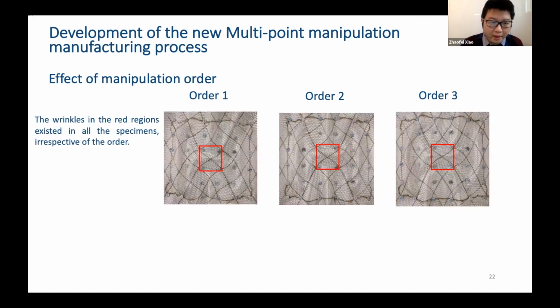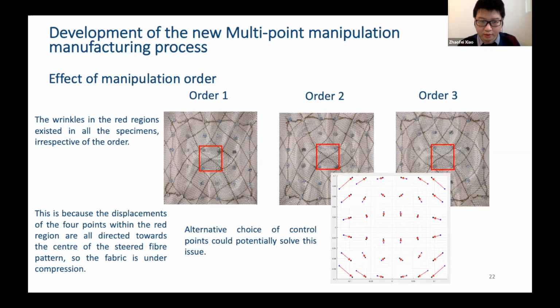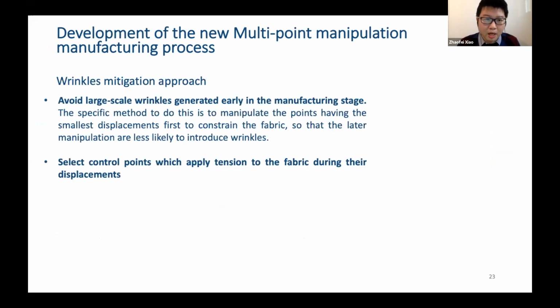And also, if we compare the final steered pattern at the center region, which is indicated by the red frame, all these 3 patterns have a large-scale wrinkle in that region. The reason is that the displacement paths of those 4 nodes at the center are all towards the center. So it will introduce compression to the fabric. Hence, the fabric is likely to generate wrinkles. So from the experiments we have done above, we know if we want to eliminate the wrinkles, firstly, we must avoid the large-scale wrinkles generated earlier in the manufacturing stage.